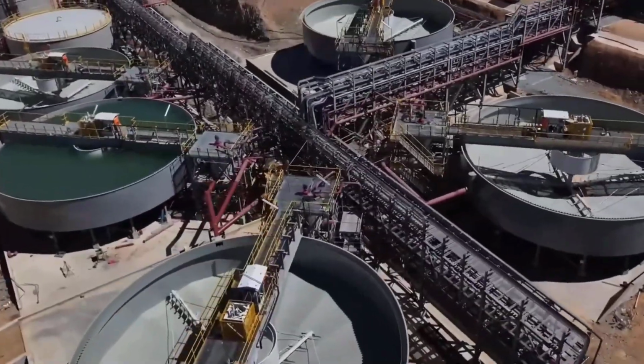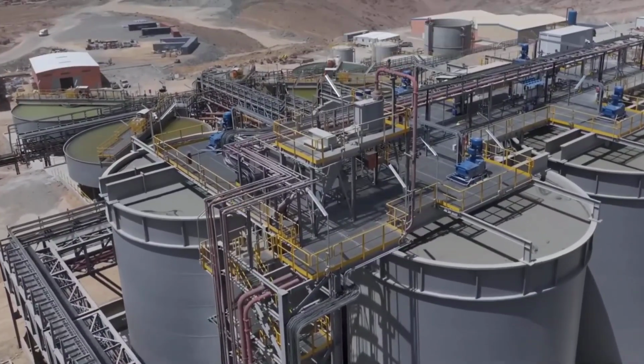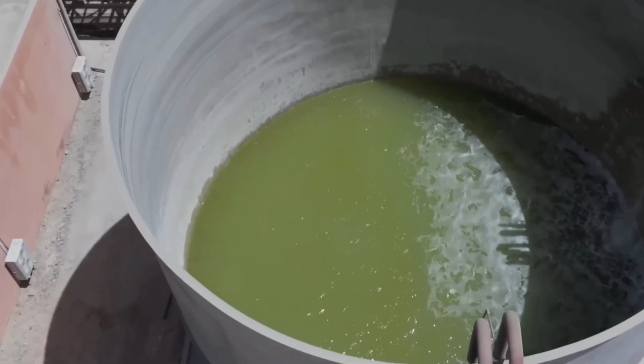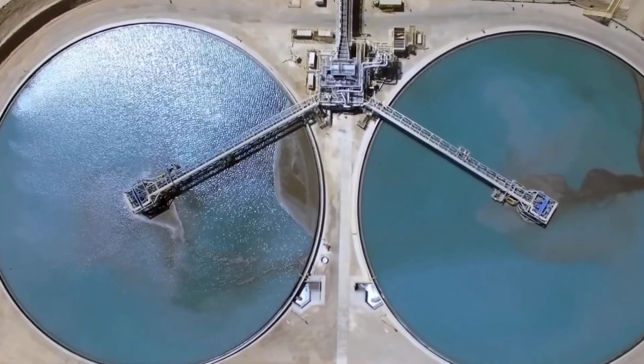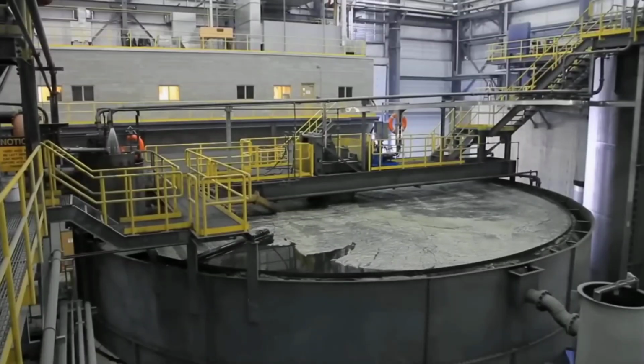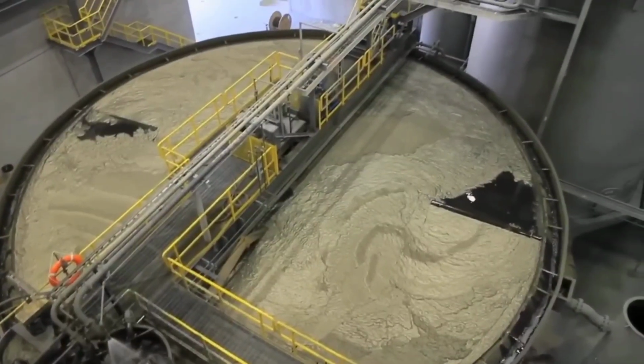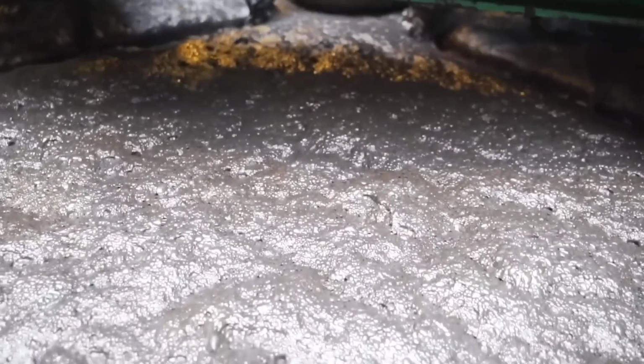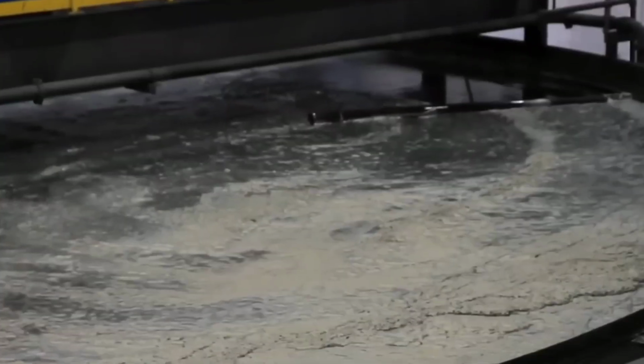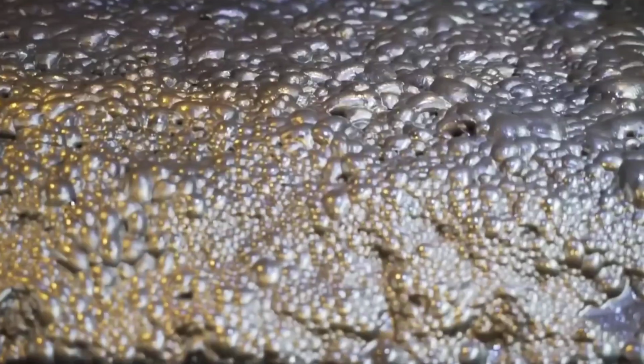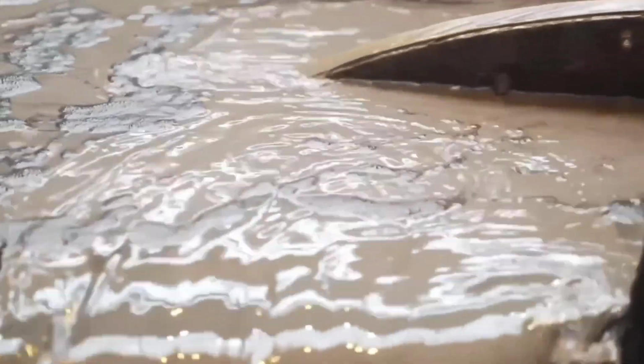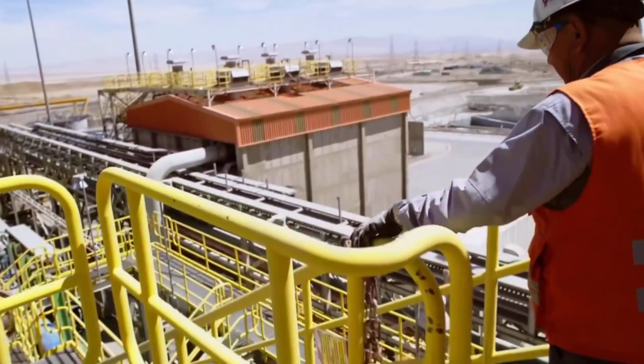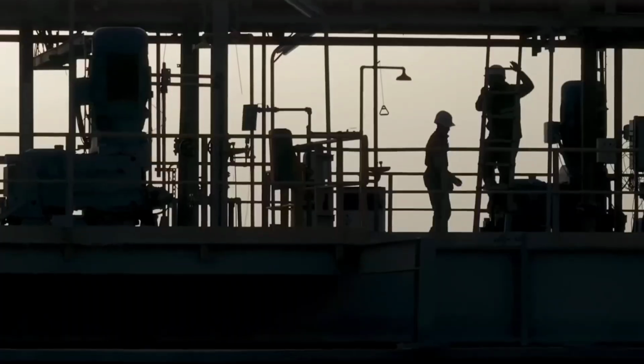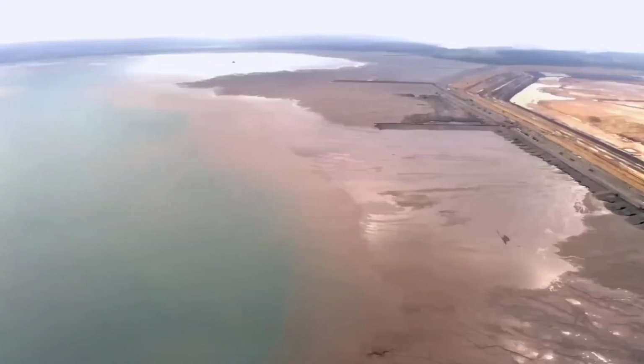The geometry of the tank, the viscosity of the solution, and the inflow rate are all carefully calculated to ensure stable settling performance without clogging or overflow. The concentrated sludge at the bottom, now with a texture similar to thick cream, is pumped into temporary holding tanks, ready for the next stage: preliminary smelting. Although it may seem simple, settling is the final natural concentration step, efficiently collecting silver-bearing particles without requiring any chemical intervention.